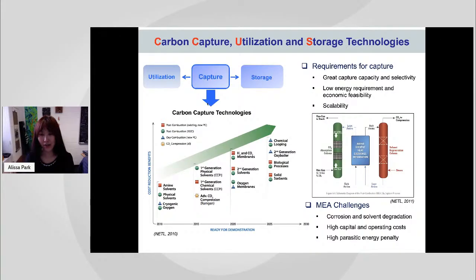If you look at this reactor, you basically need to put energy into the red reactor, which we call the solvent regeneration column. So by going downhill for CO2 capture, and by putting energy in, you release the CO2 and regenerate the liquid solvent, and put it back to capture additional CO2. This is the overall process.